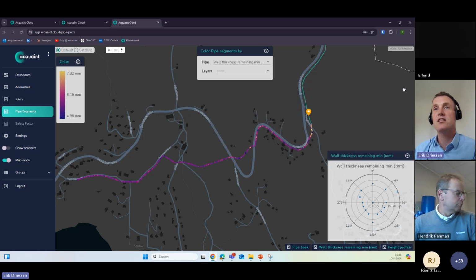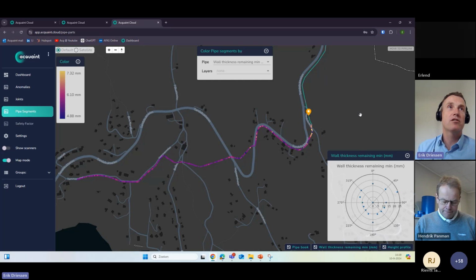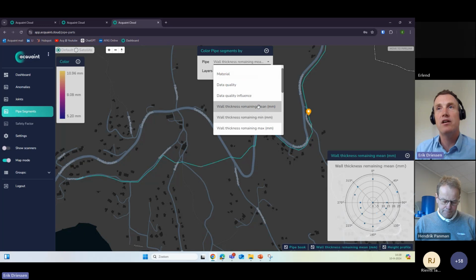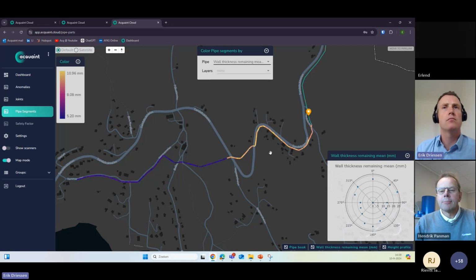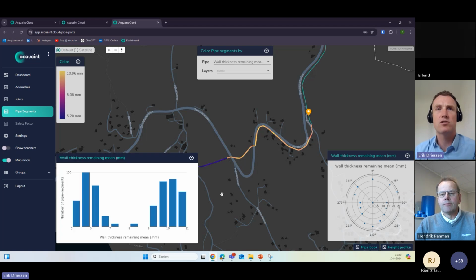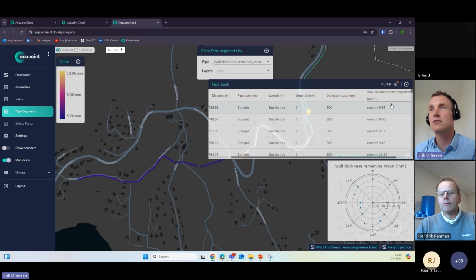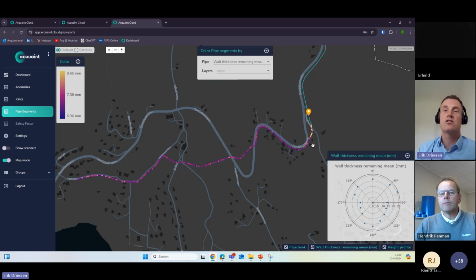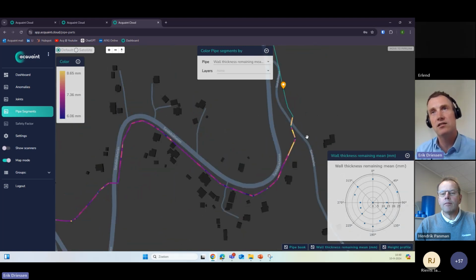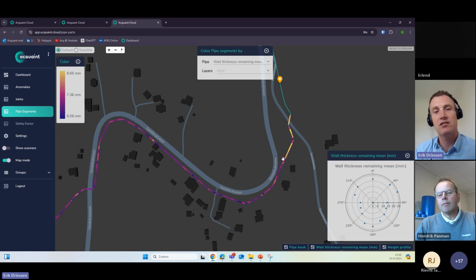So let me open the pipe book again and go to the second layer, which is the ductile iron itself, basically the most important part of the pipeline, of course. What you see here from the start till the end is that the wall thickness ranges from 5 up to 7.3, which is the color code. And this is again the minimum wall thickness. So let's go to the average one. I'm surprised that I see a jump here again because the ductile iron should be stable. Let me see, no, it went back to the cement. So this is the average thickness of the ductile iron, which ranges from 6 to 8. As you can see, at the start the average is a little bit thicker, so I can imagine these are a bit newer pipelines, maybe installed not so long ago.